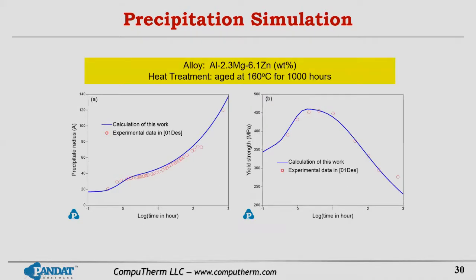I'll give you a quick example. This is the simulation for aluminum alloy 7000 series, and this slide shows the particle size evolution and the yield strength evolution with time when the heat treatment condition is 160 degrees C for 1000 hours.